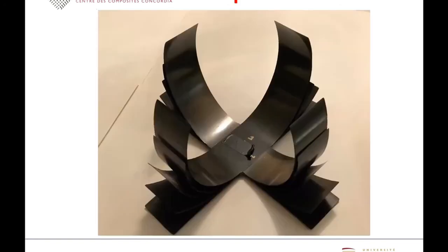And another thing that we have done is that we also make the so-called composite flower. You can see that these are carbon epoxy, and you have 5 petals. The petal here at the center curves more than the next petal and the next petal and so on. So that is basically the same principle. It's the same that you use the 0-90, but you vary the thickness of each of these different petals. By the time you finish, cool it down, you can have this particular shape.